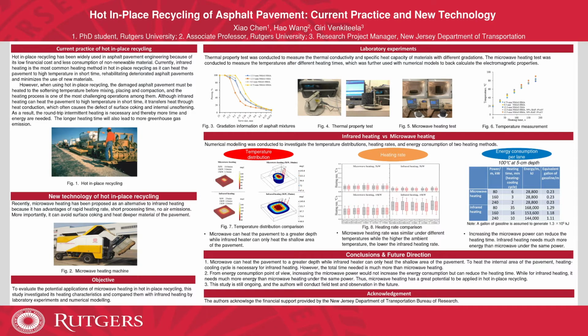So after obtaining the material properties, the numerical modeling was conducted to compare the heating characteristics between microwave and infrared heating, including their temperature distribution, heating rate, and energy consumption. As shown in figure 7, when the power increased from 5 kilowatts to 15 kilowatts, the time required to reach the same temperature for microwave and infrared heating decreased by around 67% and 92% respectively. So it shows that the effect of power on the infrared heating is more remarkable than the microwave heating.